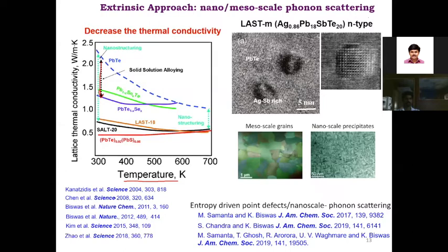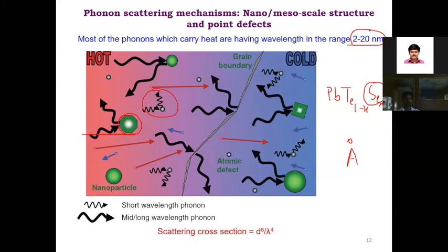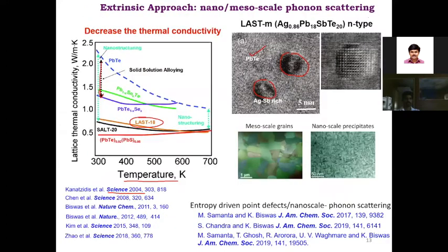But when this paper came in 2004, for the first time they showed ultra low lattice thermal conductivity in this LAST-18 material. LAST means it has lead for L, then A for antimony, S for silver, and T for tellurium, because this is a lead telluride based material where the matrix is lead telluride, but it has silver and antimony rich nanoprecipitates, which have a similar size to the wavelength or mean free path of the heat carrying phonon. Once you have these nanoparticles embedded in a matrix, you can scatter phonons heavily and give rise to ultra low thermal conductivity.